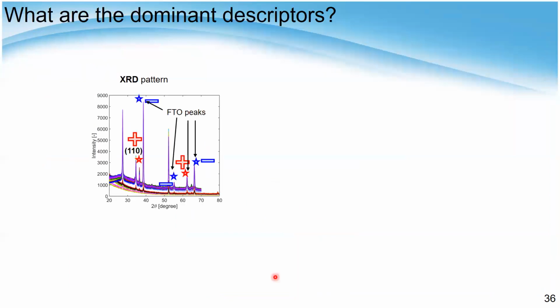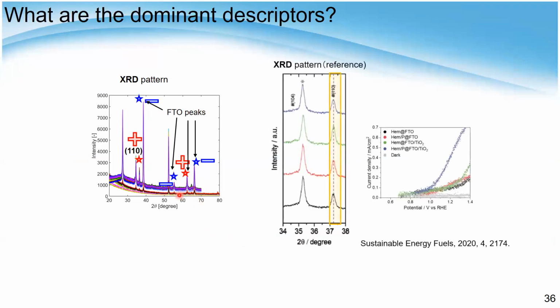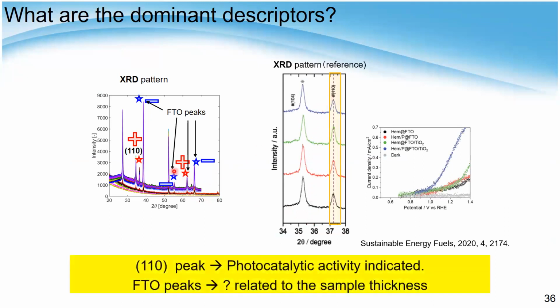And also looking at the XRD peak, there are several indications, but one of them I focused on is the 110 peak, here. This is a minor peak, and we didn't care for it much. But looking into the papers, some researchers mentioned that this peak has a strong correlation with the photocatalytic performance.